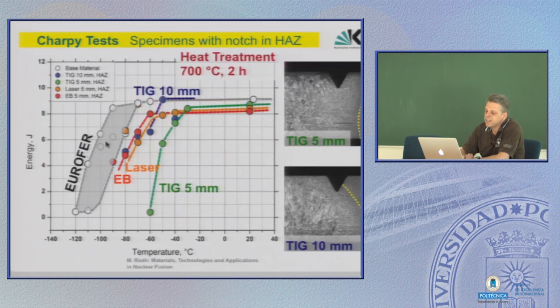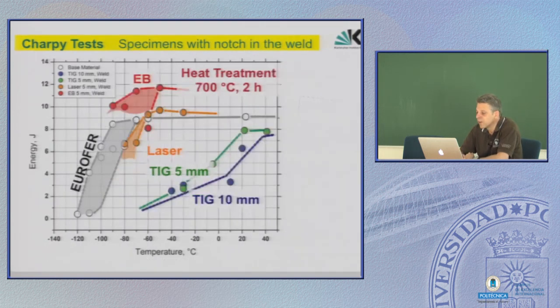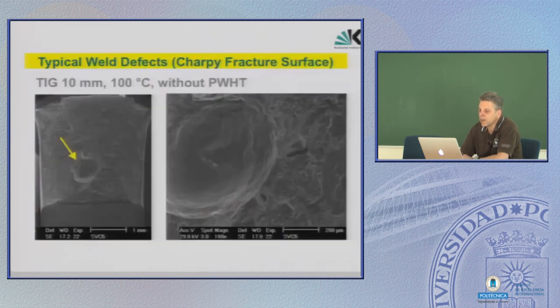Again, the same test with notches in the heat affected zone. Electron beam and laser beam are not as good as the base material, but well, you could still live with it. But here also tungsten inert gas welding, at least with the thick plates, doesn't show so bad. Nevertheless, the weld center doesn't perform good, so forget about welding here.